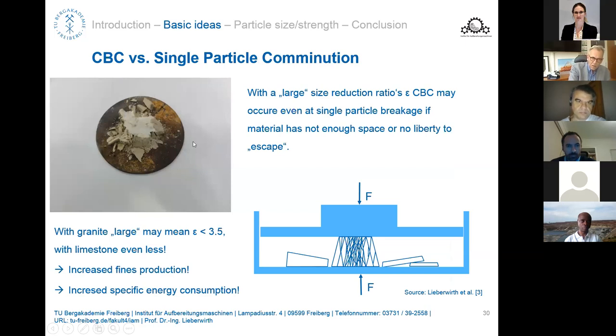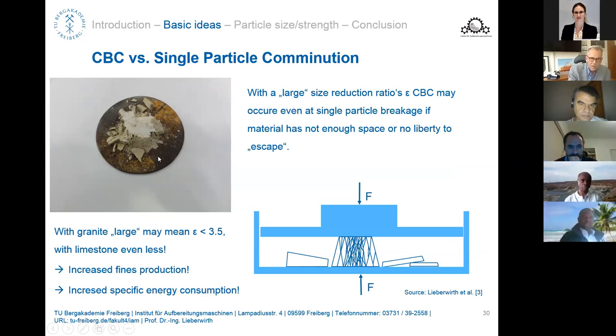We did also some other single particle comminution tests, and I'm coming now closer to our topic, the piston die test. We did some investigations with the piston die here, also earlier, with different materials, with quartz, with granite, with limestone. What you can see here is a particle which had originally the size of 300 millimeters. So the reduction ratio here: the original height, as mentioned, was 300 millimeters. We pressed it to a gap of 80 millimeters.